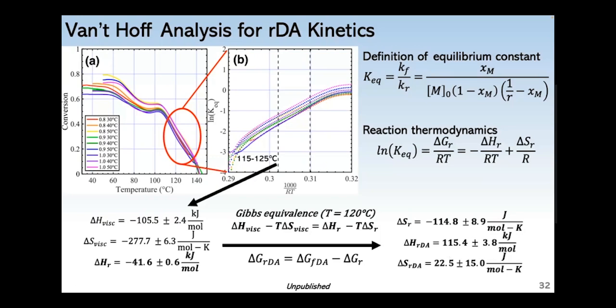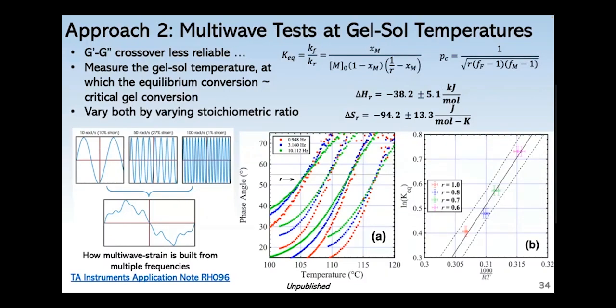But truthfully, I still hadn't convinced myself that this previous procedure had accurately determined the reaction thermodynamics. So I took a second approach, and that was to conduct multi-wave tests. So I mentioned earlier the G prime, G double prime intersection point is just one way of measuring the gel point. A more exact way in dynamic rheometry is to measure at multiple frequencies and then find the frequency independence point from the phase angle. But rather than doing multiple tests, these multi-waveform tests overlay multiple strain profiles instead of the usual single profile. And during the test, the material response is broken up into separate frequencies.